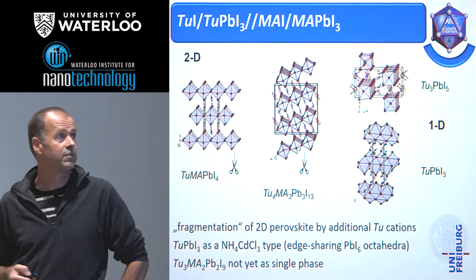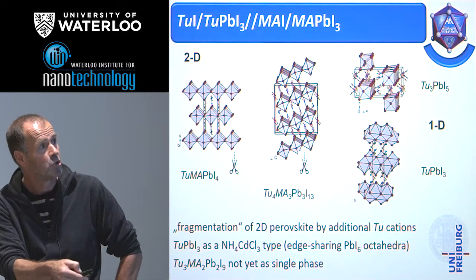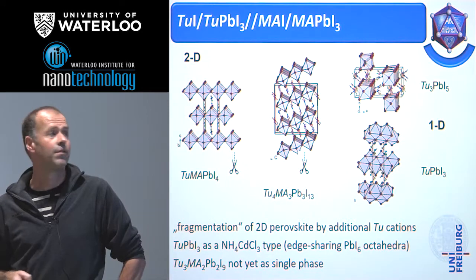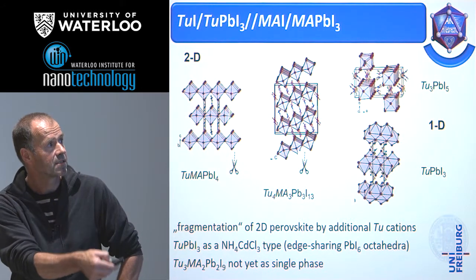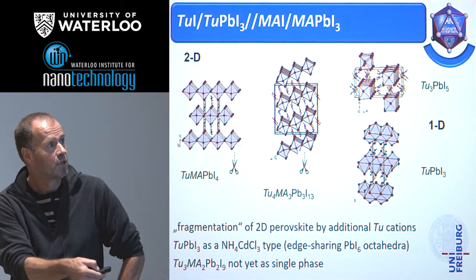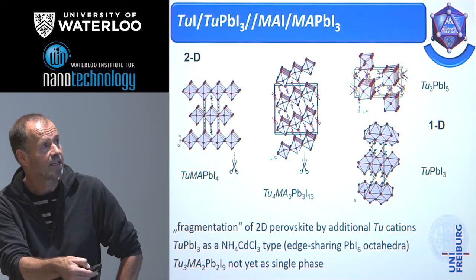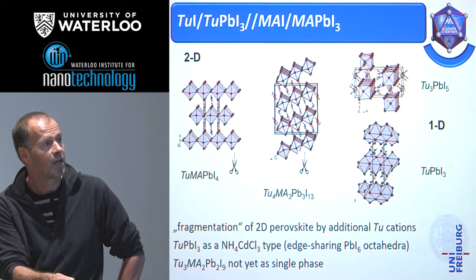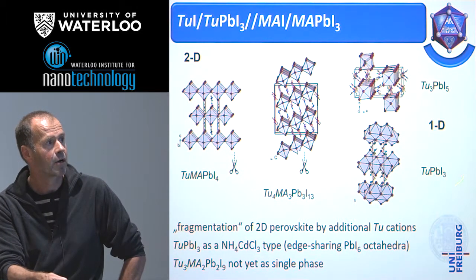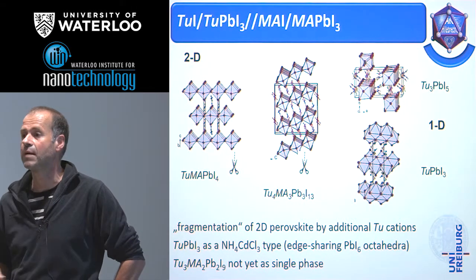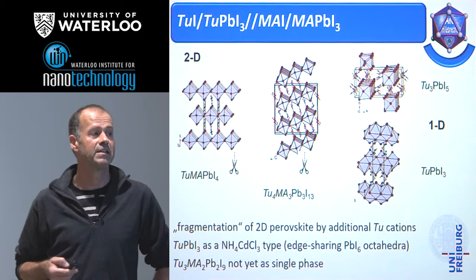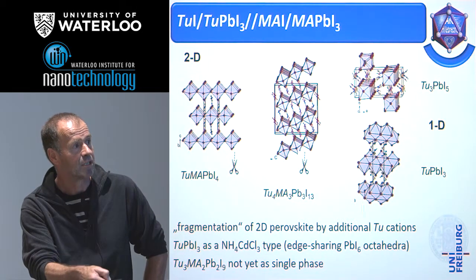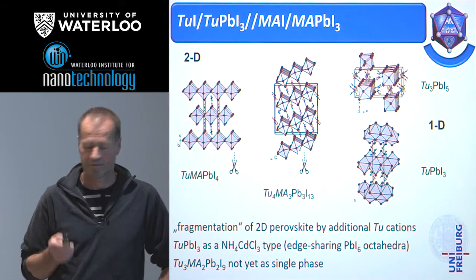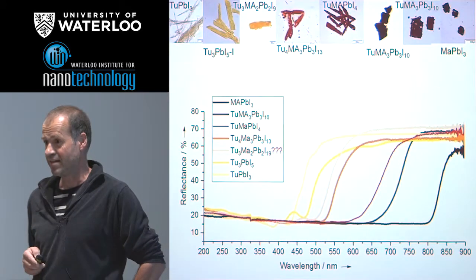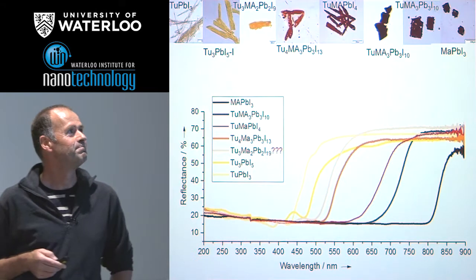We could continue it from a two-dimensional structure to one-dimensional structures. That means we can cut pieces from the layer structures to trimeric units, to single chains, or if we only have the thiourea compound, this is an ammonium chlorocadmate type, which is a different type of perovskite structure where we have linear structures by double chains of these octahedra. And yeah, I come to an end.